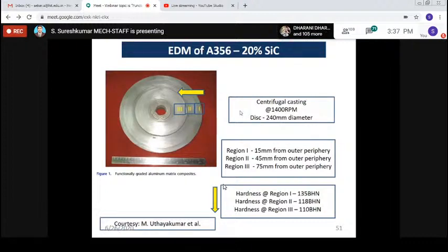First, region 1 is 15 mm from the outer periphery, region 2 is 45 mm, and region 3 is 75 mm from the outer periphery. And as I told you, the hardness value is reducing from the outer region. I mean, where the rich mixture is available, the hardness value is high. As we move towards the least reinforcement section, the hardness value is reduced gradually.